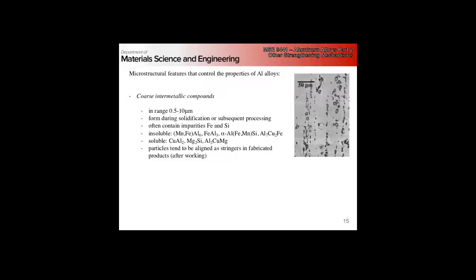So we started on Wednesday looking at some of the microstructural features that control the properties of aluminum alloys. The first microstructural feature was the presence of coarse intermetallic compounds. For the purposes of the upcoming discussion, we'll consider these in the range of 0.5 micron to 10 microns. They form during solidification and processing. They tend to align in stringers as a result of mechanical fibering.